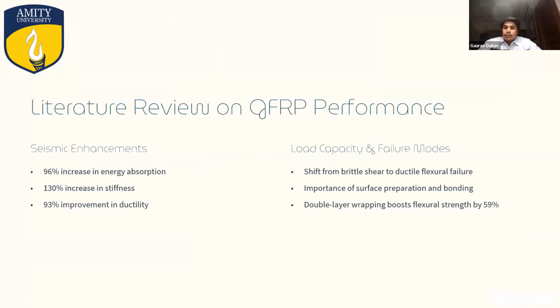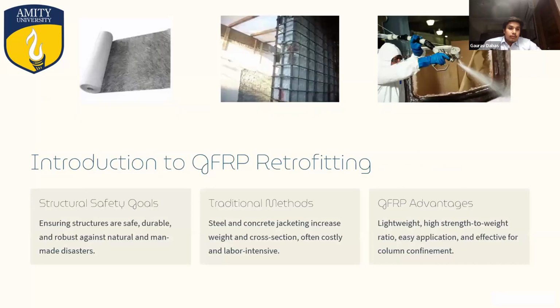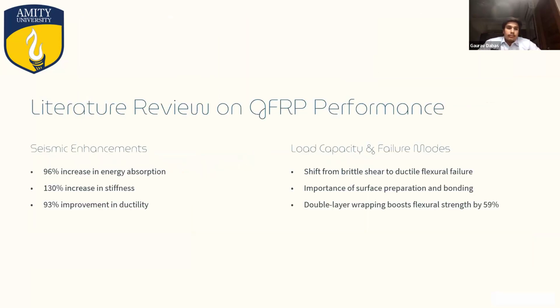Now, a literature review of the GFRP performance. Studies have shown impressive results with GFRP strengthening: up to 130% increase in stiffness, 93% improvement in ductility, and 96% gain in energy absorption. They are crucial for earthquake-resistant design, which is very important in India and the seismic zone that we have. GFRP also changes the failure mode from brittle shear to ductile flexure, which is safer. Double wrapping has been shown to increase flexure strength by 59%.